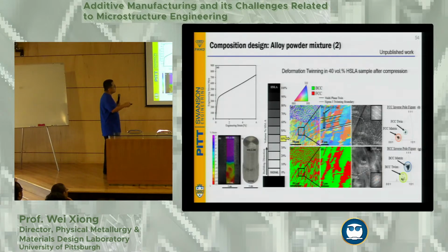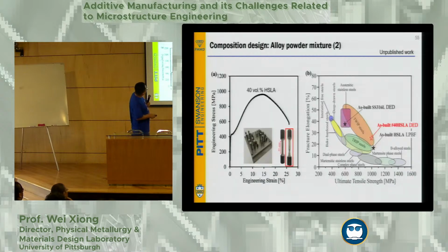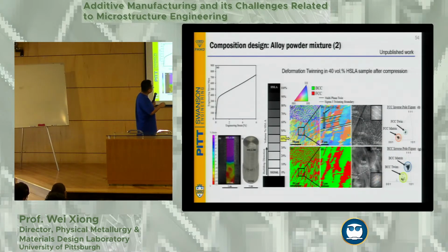So that's the part where we did a lot of characterizations, EBSD. I don't know if I showed it, I probably skipped that slide, but we did mapping with the EBSD from the bottom to the top, and we find 40% is very interesting.